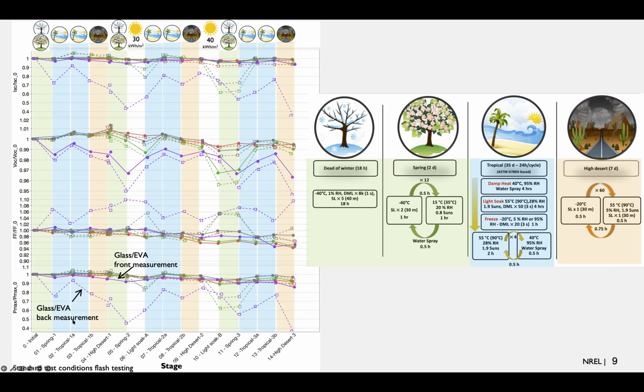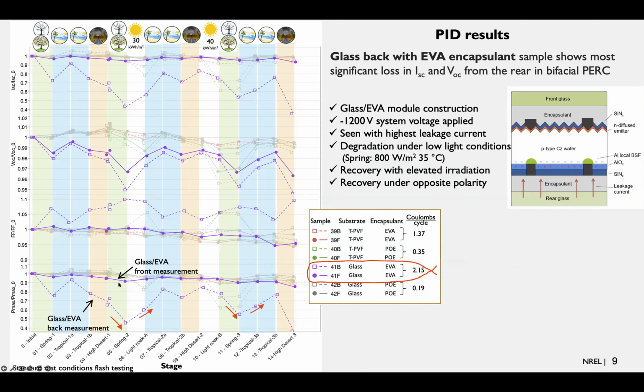Okay, so I'd like to focus the attention on the glass EVA front measurements and the glass EVA back measurements as shown here. So I've highlighted those on the table here and dimmed all the other data to help us see what we're talking about. What we notice is that these particular modules degrade a good deal. Here we're looking at flash tests from the rear, and in the solid line, flash tests from the front after the given stress sequences. We're seeing that the modules with glass back and EVA encapsulant show the most significant loss in ISC and VOC from the rear in bifacial PERC.